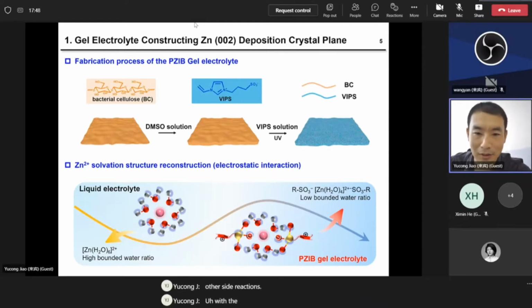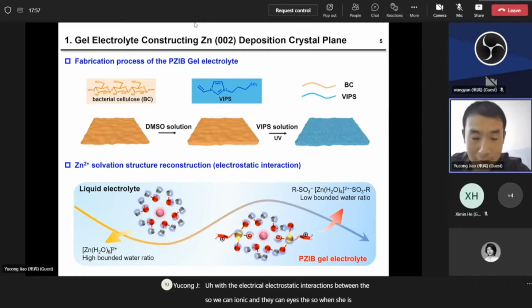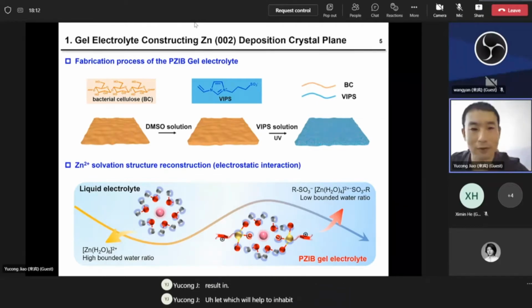With the electrostatic interactions between the sulfonate ionic and zinc ions, the solvation structure can be reconstructed, and there are only 4 water molecules surrounding the zinc ions, which will help to inhibit the side reactions occurring on the zinc metal.